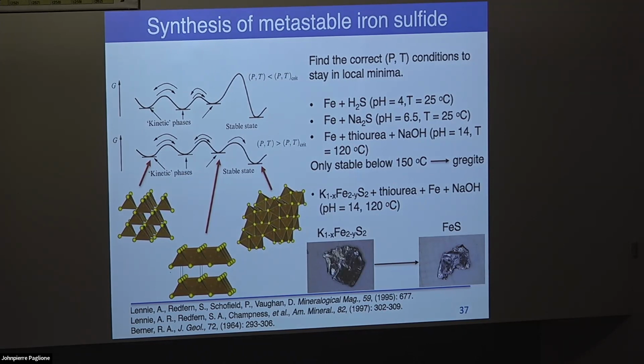But if we wanted to measure resistivity, we wanted to make single crystals, so we wanted to see if there was another way to do this. Another way is to take a related compound, which is essentially potassium intercalated iron sulfide. So it's basically the same layer structure, but in between the layers are potassium ions. Single crystals of this are a thermodynamically stable phase, which you can make from a self-flux reaction of potassium, iron, and sulfur. And you can take these single crystals and turn them into this layered iron sulfide just by removing the potassium ion between the layers.